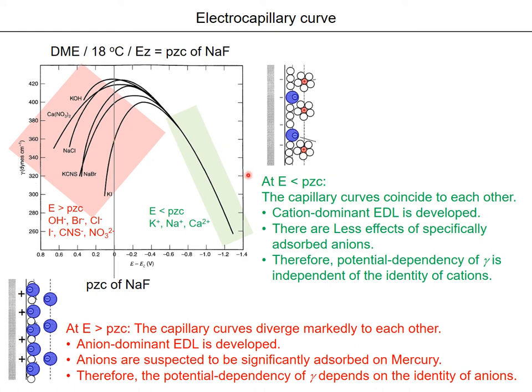Some interesting things are discovered. For the negative potential, which is more negative than the point of zero charge, every source goes to the same curve. However, you can recognize that the curves are not coincident to each other for the positive potential. Here are the reasons for that.